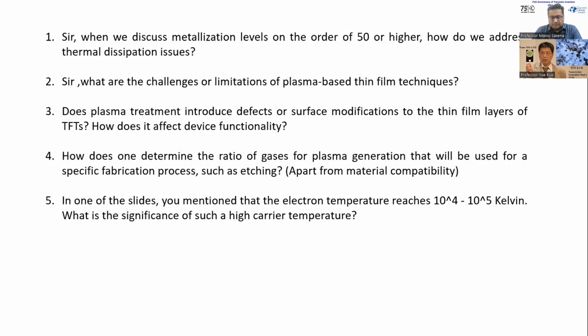The fifth question: in one of the slides, you mentioned that the electron temperature reached 10^4, 10^5 Kelvin. What is the significance of such a high carrier temperature? The electron has to heat molecules to dissociate them. The plasma we are talking about here we call cold plasma. Actually, 10^4, 10^5 K is typical in plasma etching or deposition conditions. Remember, electrons have very small mass. You have high energy because of the high temperature, and that's enough to break down the bond or attach the bond and form various compositions.